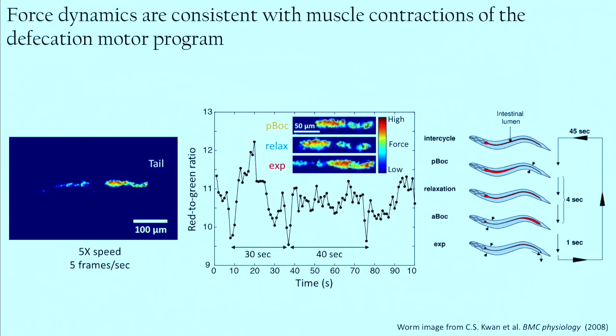And then in addition to static images, we can also look dynamically at the force. So here the color that you're seeing actually corresponds to the force being exerted by the worm as it's excreting the food. And we can see that the red to green ratio changes with approximately a 30 to 40 second periodicity that corresponds to a posterior body wall contraction, or PBOC, relaxation, and then expulsion. So quite similar to the digestive system that we would experience as humans.